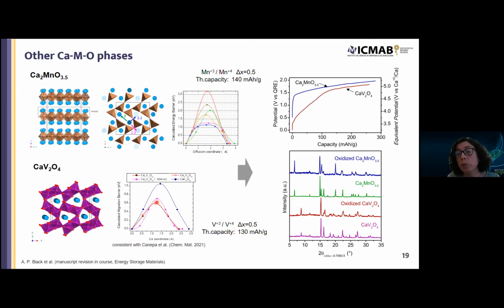So we prepared those compounds and we oxidized them electrochemically. And the first thing is that the potential at which they oxidize is huge, equivalent to 5 volts versus calcium metal. So we will for sure have a lot of electrolyte decomposition here. But when we did diffraction of those materials, we saw that there were changes in the diffraction pattern. So really there is something going on in the material. So this is the pristine calcium vanadium oxide, and this is the oxidized phase, and the same for manganese.